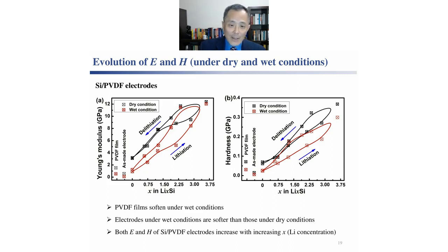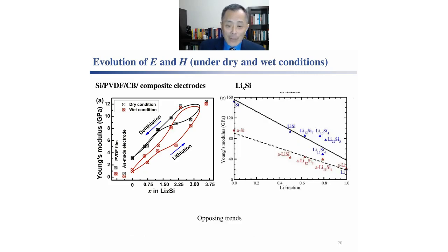More importantly, we saw that the modulus and hardness increases with increasing lithium concentration. And this is opposite from what we know about lithium silicon alloys. For the alloys, the modulus would decrease with increasing lithium concentration. So what's going on?